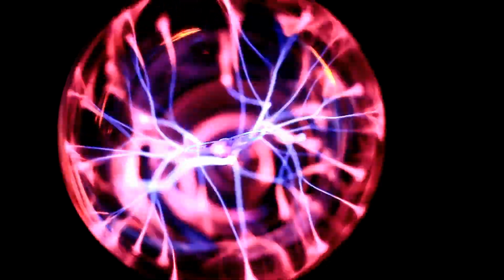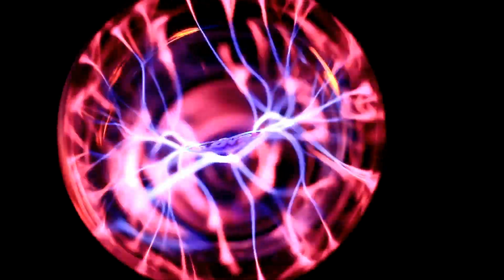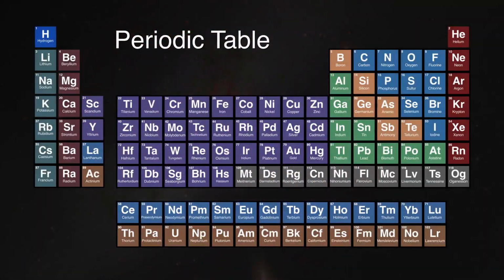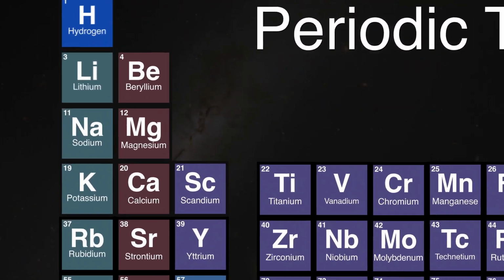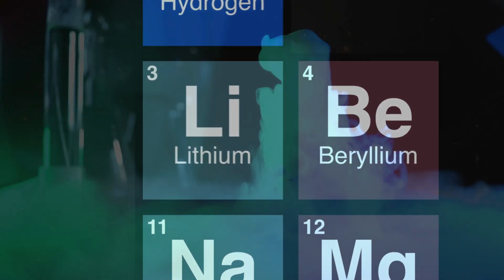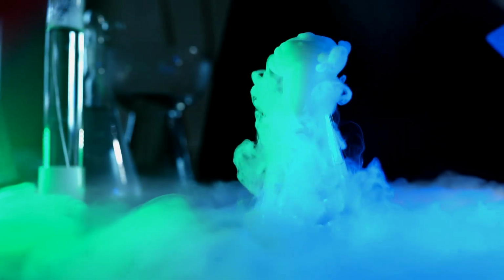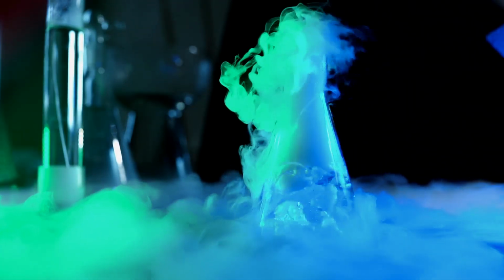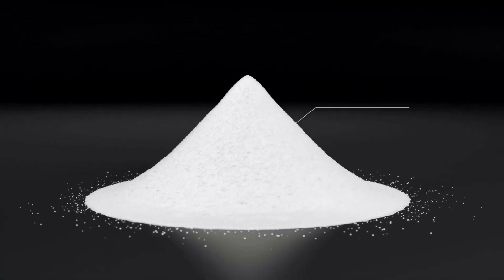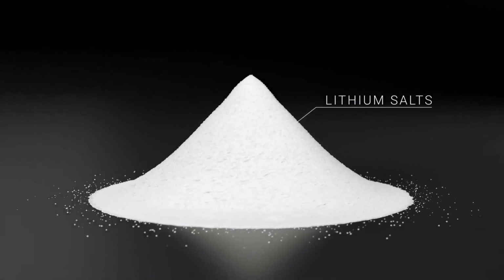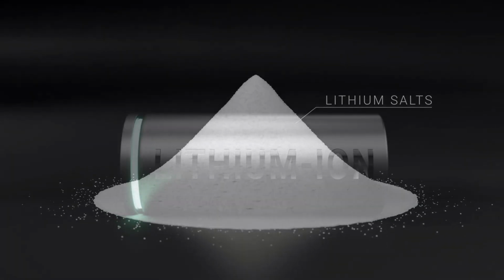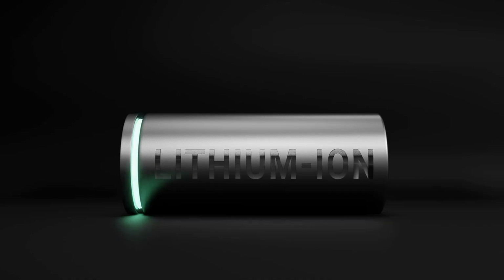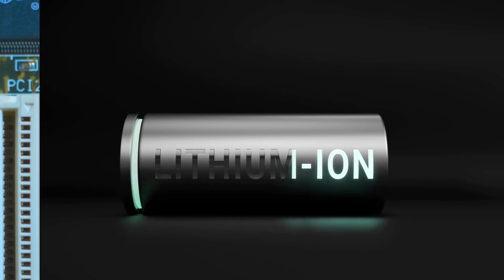Lithium releases more energy per electron than any other metal, producing the highest voltage. It's also the least dense metal, a perfect combination for a high-energy density battery. But pure lithium is dangerously reactive. To use it, Whittingham replaced the water-based electrolyte with a risky organic solvent. This unlocked lithium's potential, breaking the voltage ceiling and delivering 2.4 volts per cell, nearly double what was previously possible.